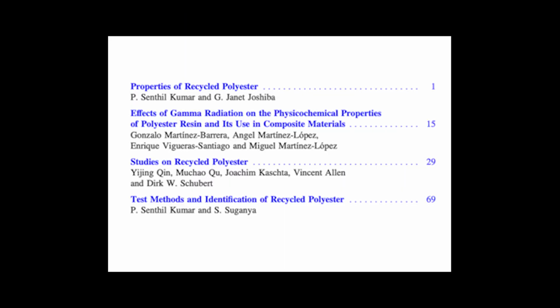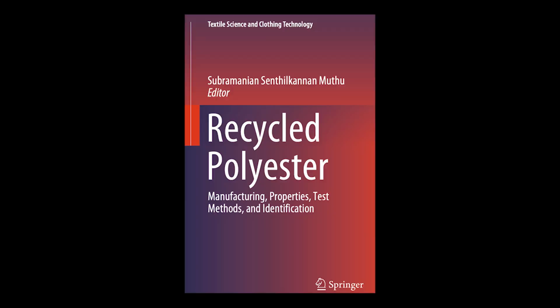So what were the key findings? Which materials actually behaved well under this high-stress industrial simulation? Which ones could be spun effectively at high pressures? The results were quite definitive, and maybe a bit surprising. The high-purity, clear recycled flakes, the rPETB, and one of the virgin materials, the standard fiber-grade homopolymer, VPET2, these two yielded the optimal spinnability. What does optimal spinnability mean in practice?